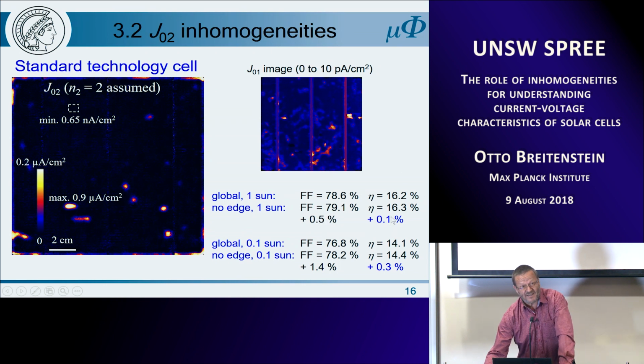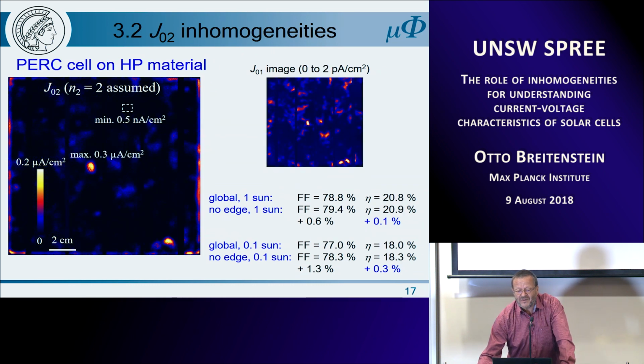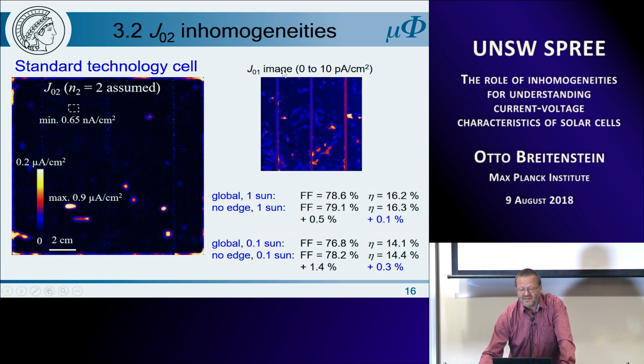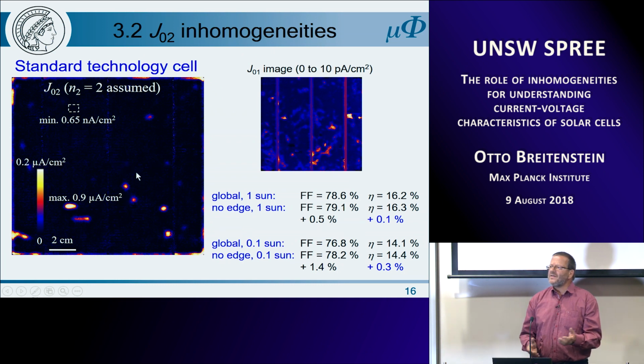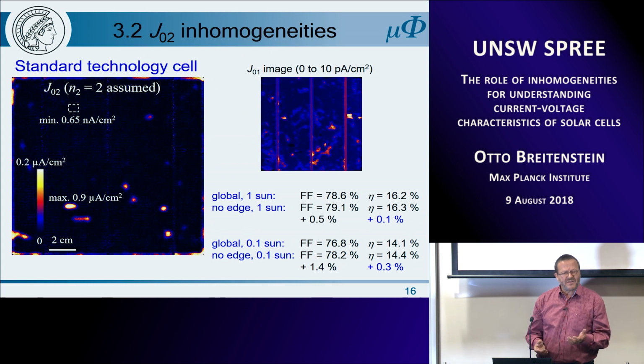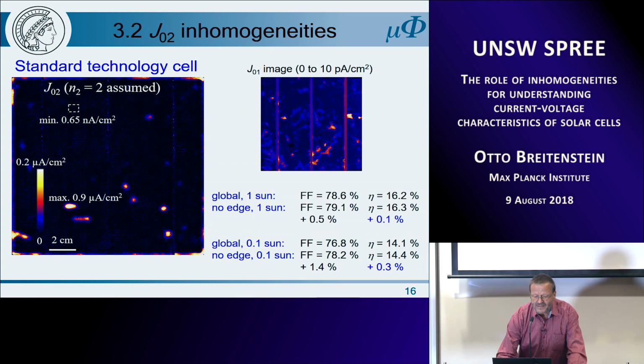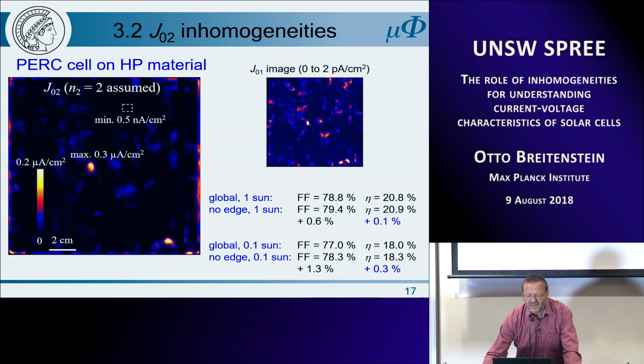However, at 0.1 sun reduced intensity, the fill factor would be increased, if we wouldn't have the edges, by 1.4% and the efficiency by 0.3%. And very similar numbers. So here at the right, just for memory, I show you the J01 image, and you see the J01 image is very different to the J02 images. And this proves that this method really can distinguish between these two types of currents. And here in the PERC cell, we have the same: only in the J02 images we have this strong edge current, which is not visible in the J01 image, and the numbers are nearly the same.